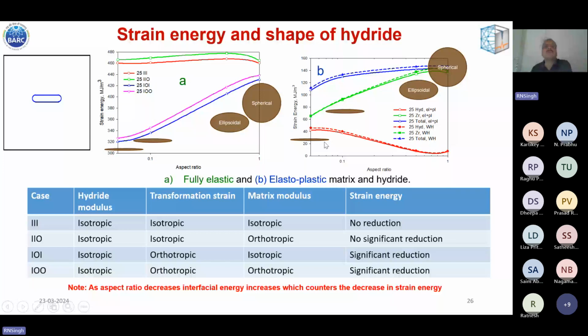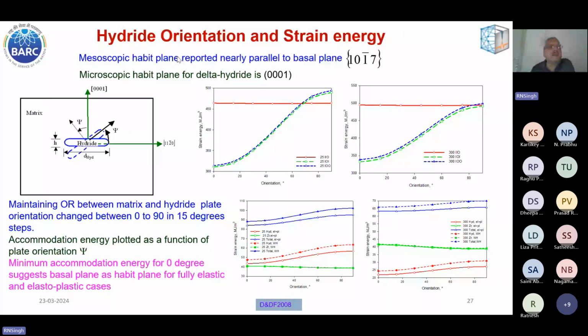The second illustration is that here, suppose you have a hexagonal zirconium crystal. This rectangle represents the hexagonal zirconium crystal, and you have a hydride plate like this. Now this green line you are seeing here is the basal plane, and 0001 is the normal to the basal plane. So what we did is we tried to calculate the strain energy of the whole system by assuming hydride orientations between 0 to 90 degrees.